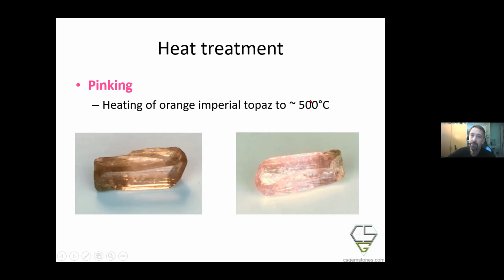And a temperature of 500 degrees is not really something that you can detect, like in the sapphire, where you heat sapphires up to 1800 degrees. You see some damage to the crystal, to the inclusions. This damage at 500 degrees does not occur, and it's almost impossible to detect this type of treatment. It is possible if you have the stone before and after the treatment.